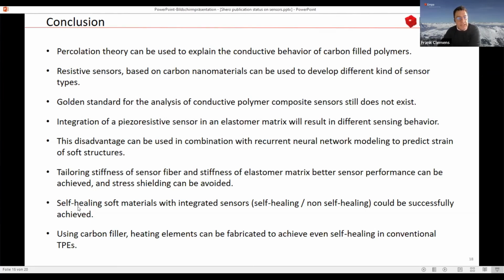We also could see that self-healing materials with integrated self-healing sensors, we already could achieve successfully. By this, I think we can really show at the end of the project the device prototype which we should make. And finally, using carbon filler, heating elements can be fabricated to achieve even self-healing in conventional TPE materials. I think this also gives a very good prognosis for using other materials instead of only self-healing materials in the future for soft robotic applications, and using the self-healing mechanism.